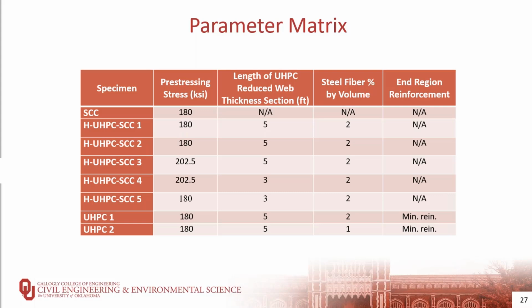In addition, 2 different fiber contents were examined for the full UHPC girders, and that was mainly to investigate their shear behavior after shear testing.